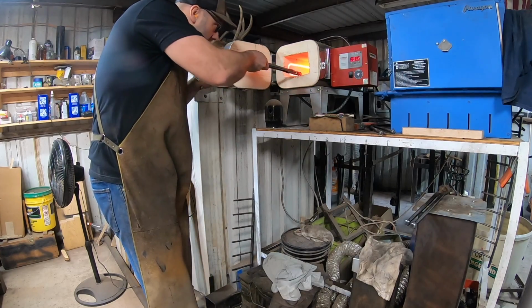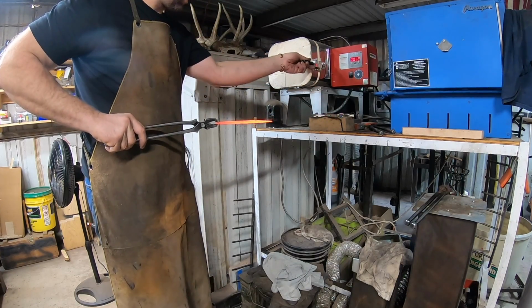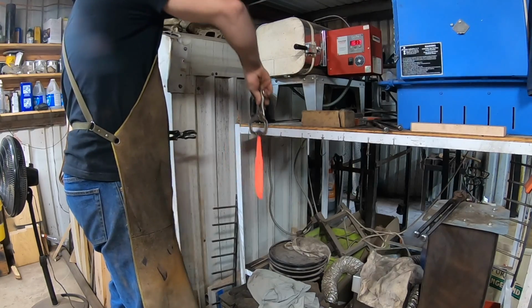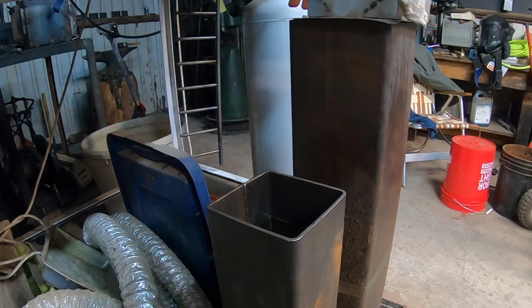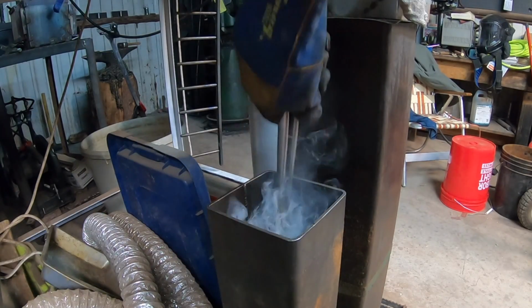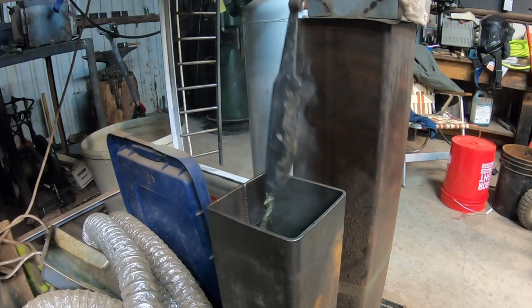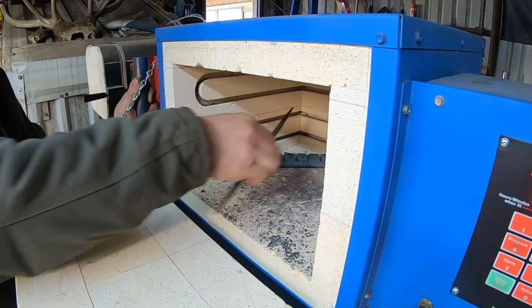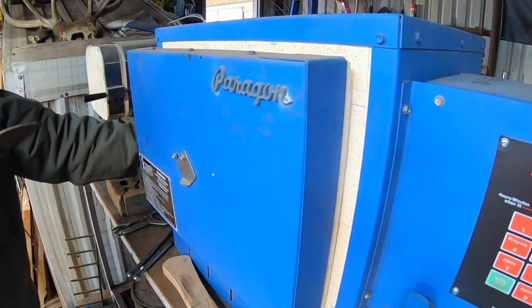Got it all forged, and we'll begin doing heat treating processes here. And then finally a quench to harden the steel. Once we have it tempered, we can begin grinding. Up to this point, there's been no grinding done. We've just forged the bevel in and the profile of the blade, and of course the tang as well.